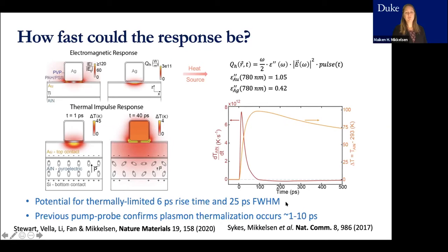We did do previous pump probe studies using transient absorption in this Nature Communication paper showing fast plasmon thermalization, 10 picoseconds, but there might be grain boundaries always in physical systems. There's a lot of other effects going on. I doubt we can get this far. That would be pretty remarkable, but I'm sure that we're not at the limit. So we're somewhere between the 700 picosecond and down to the tens of picoseconds.